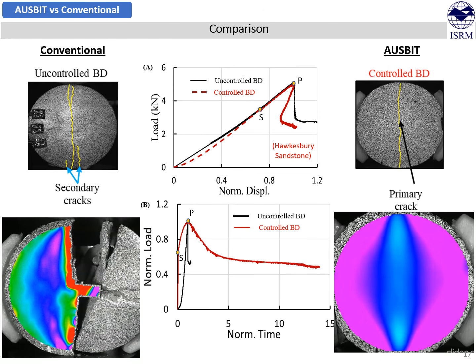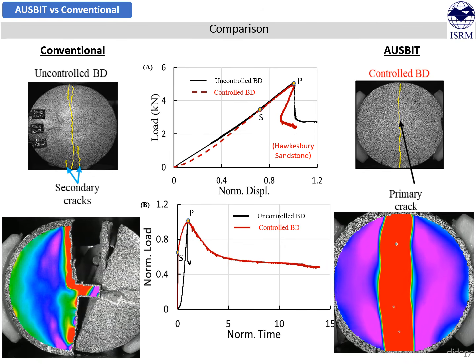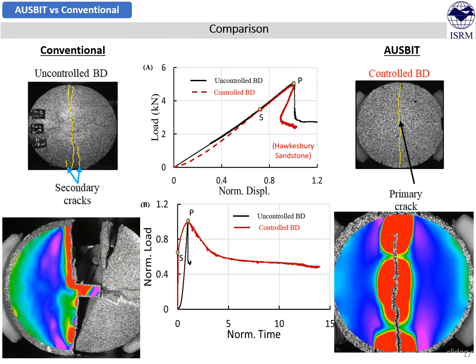Now, the immediate benefit of this controlled cracking can be seen from figure A, that is the load versus displacement response. In the conventional approach, the disk cracks immediately after reaching its peak load P, and the cracking pattern also includes secondary cracks indicating the release of excess strain energy. The same disk specimen in controlled AUSBIT experimentation can produce true post-peak behavior with snapback response. And there is no sign of secondary cracks. That means the specimen has consumed the amount of strain energy that is required for the vertical diametrical crack, and the excess strain energy has been successfully removed to enable the snapback response and to capture the true post-peak behavior of the disk specimen.